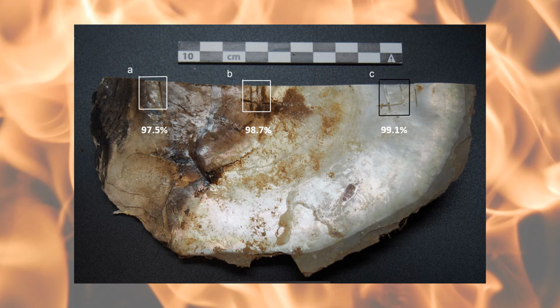any way. And because of that, and given the controlled conditions, we thought, okay, well, let's take some samples for X-ray diffraction and have a look. And what we found was actually really intriguing. So the percentages that I've written up there are percentages aragonite. So mother of pearl is always constructed of the aragonite form of calcium carbonate. And under extreme circumstances and extreme heat, that should recrystallize to calcite.